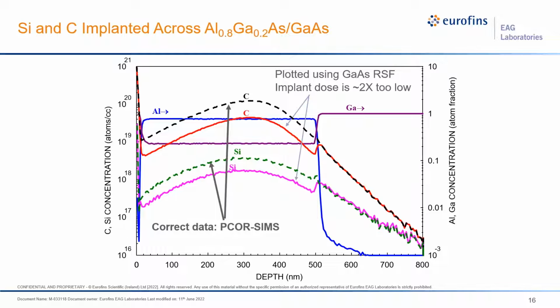We verified the accuracy of our PCOR-SIMS corrections by measuring ion implants of carbon and silicon across the interface of an aluminum 0.8 gallium 0.2 arsenide structure. Plotted using the solid lines are the carbon and silicon implant profiles using only gallium arsenide sensitivities. There's a large discontinuity at the AlGaAs interface, which is an artifact due to the change in sensitivities between the two layers. However, after applying the PCOR-SIMS corrections at each data point in the dashed curves, the anticipated implant profiles are obtained with no discontinuities at the interface. As noted on the slide, without PCOR-SIMS corrections in the AlGaAs, the concentrations of carbon and silicon would be too low by a factor of 2. The next slide shows the ramifications of the effect of the PCOR-SIMS corrections on an N-type DBR.